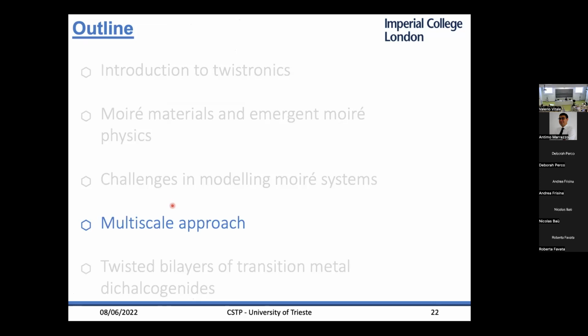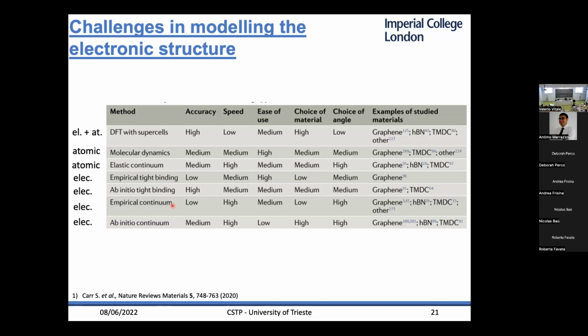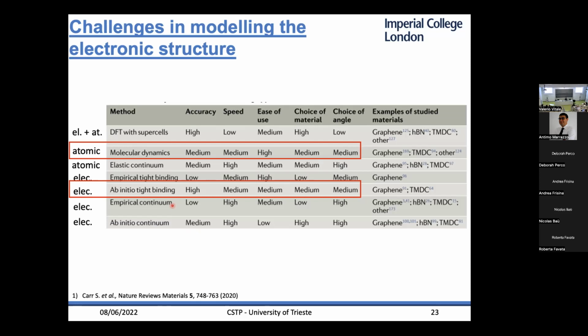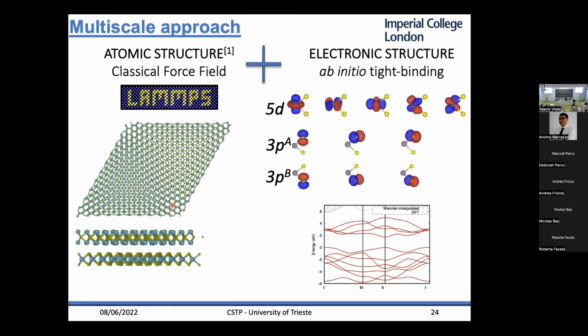So our approach to study this system, we wanted to study a large class of Moiré materials, in particular transition metal chalcogenides. And we wanted to study different twist angles, different combinations. So we really couldn't go with DFT. So our approach was basically to combine these two different methods. We use classical force field or molecular dynamics for the atomic structure. And then we use the ab initio tight binding that we developed for the electronic structure. I'll talk mostly about the ab initio tight binding, because the classical force fields were already implemented in LAMMPS. So our approach was this combination of two different methods.